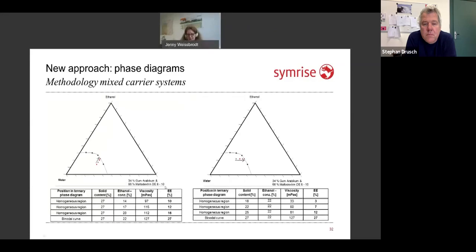But normally our spray drying is done not with just maltodextrin, it's done with a mixture of gum arabic as an emulsifier and maltodextrin. So the next question was, could we establish these diagrams with a mixture of gum arabic and maltodextrin if we just treat this mixture as one substance within our mixing diagram? And it was possible. We could establish binodal curves in this diagram with a mixed carrier system. And now the question was, if we come near from the homogeneous region to the binodal curve, will our encapsulation efficiency be improved? And this is what we did.